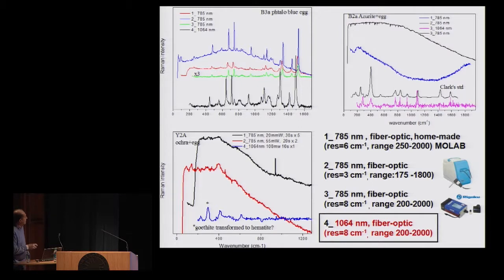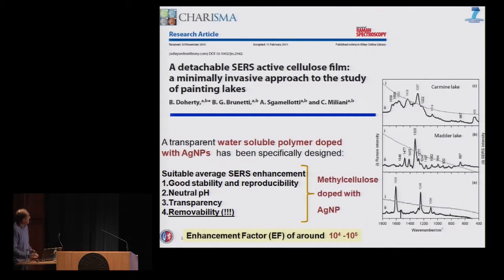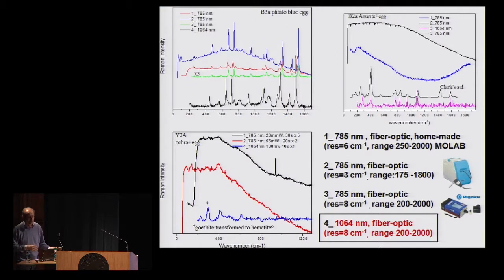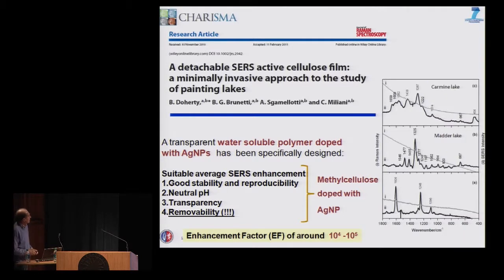We have recently acquired a portable spectrometer that works with excitation at 785, but also at 1064 nanometers. And this is a comparison. This is the spectrum of phthalocyanine blue layered in egg with our MOLAB Raman, and this is using the new Raman with the 1064 nanometer excitation. And this is ochre layered in egg, the spectrum obtained using our MOLAB Raman, and this is the spectrum obtained using the excitation in the near infrared. We did not carry out measurements using this device yet, but the hopes to be successful in the future are quite good.